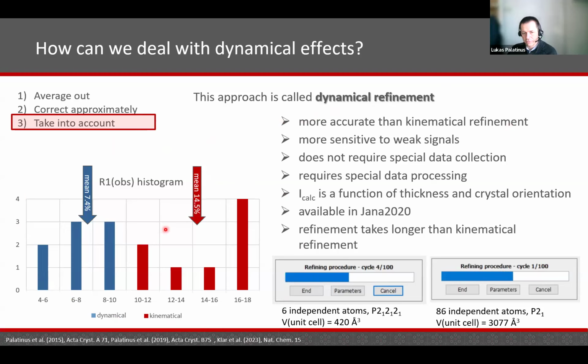These are 8 structures carefully refined kinematically and dynamically, and this is a histogram of R factors obtained with the kinematical refinement. So you see we are somewhere between 10 and 18%. And this is actually a very good set. So typical values for kinematical refinement are rather around 16 to 18%. And then when dynamical refinement is applied, the R factors, which express the quality of the fit, drop significantly to something like on average 7.5 or 8%.